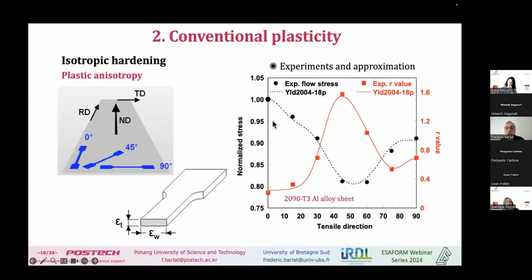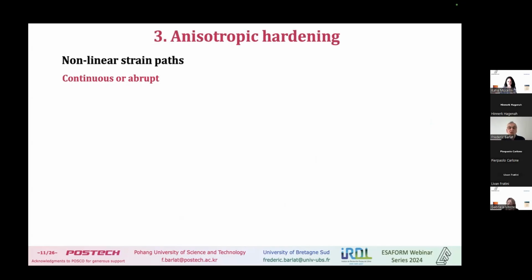Anyway, this is a 3D yield function. The 2D model would still give a good agreement, but not with the detail that we see here, because the 2D model would take only 3 points at 0, 45, and 90 degrees, 3 points for yield stress and 3 points for R value as data to identify the model. So this was, I would say, conventional plasticity.